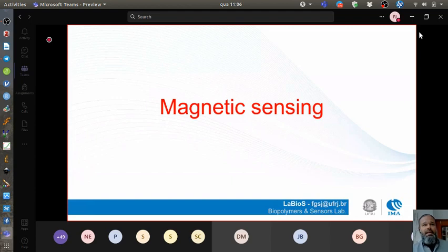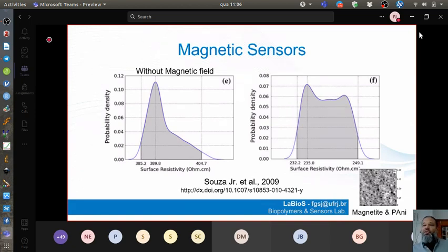Regarding the magnetic sensing, when we are thinking about magnetic sensors, we must think that they are often used for security and military applications, such as detection and localization of ferromagnetic or conducting objects. So it's a very, very interesting field. Our first work related to this subject was performed modifying the surface of magnetic nanoparticles. In this specific case, we used magnetite, which was modified with PANI. Here we have the AFM of this sample. And then we studied this material in the presence of a magnetic field and without a magnetic field.